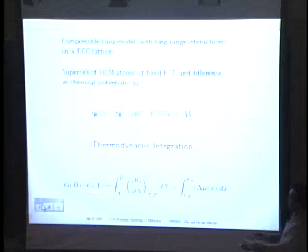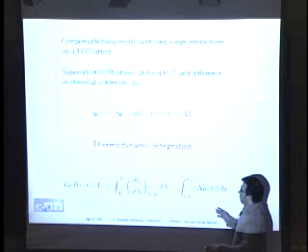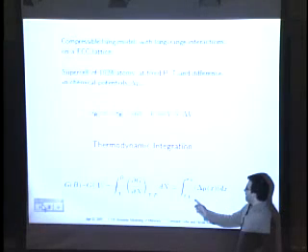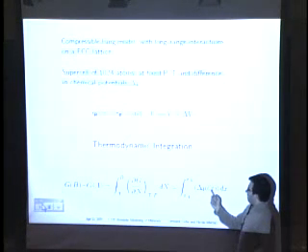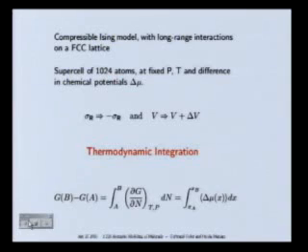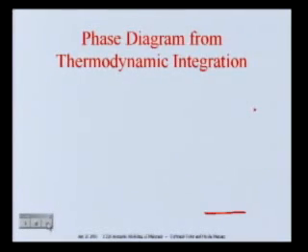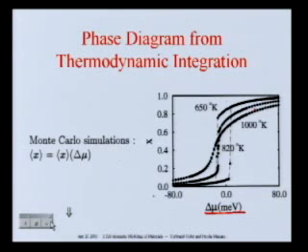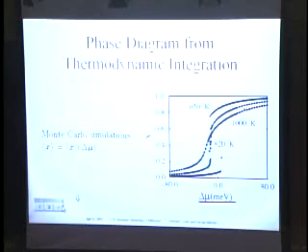You need, in thermodynamic integration, to calculate the free energy difference between two concentrations, the integral of the average chemical potential for a given concentration. So the only thing that you have to do is really look at this curve, turn it around if you want, so that you have x as a function of mu, and say for the 1000 Kelvin case, you'll have something like this.